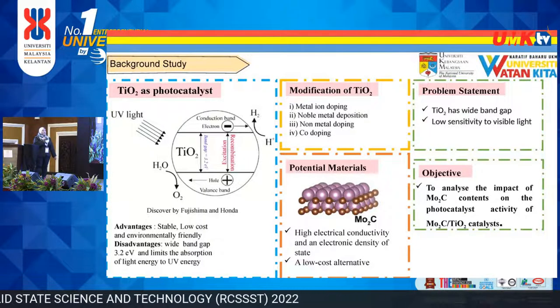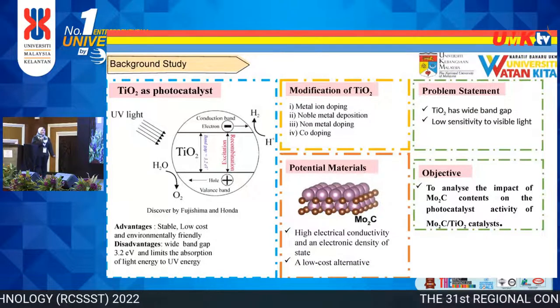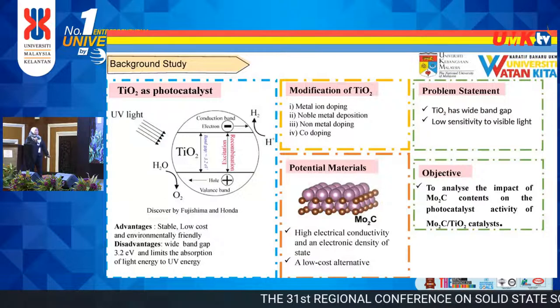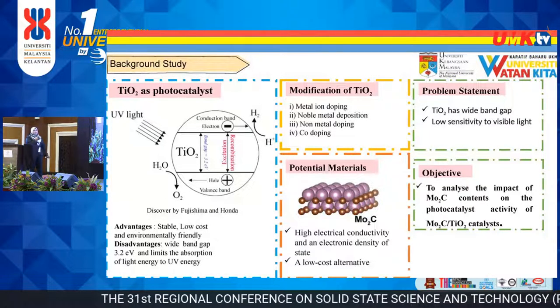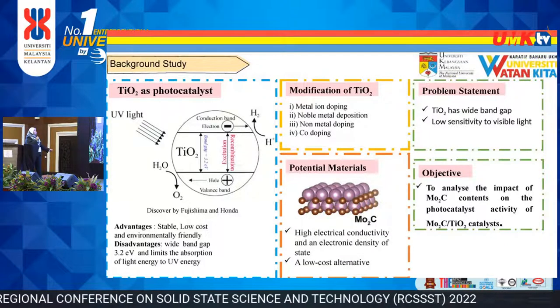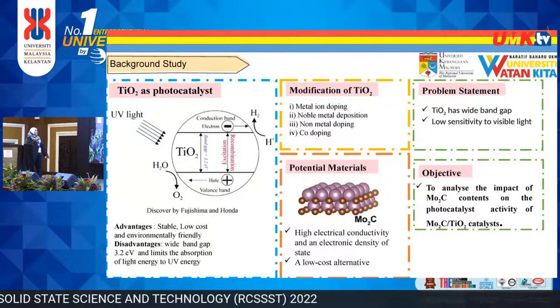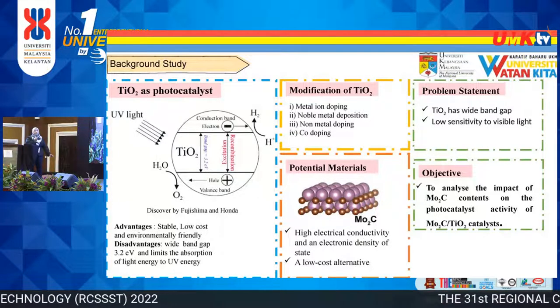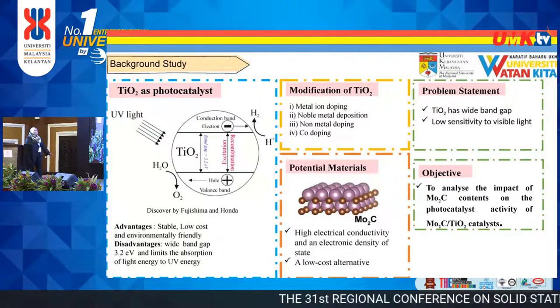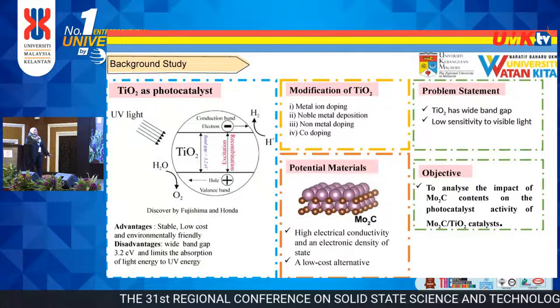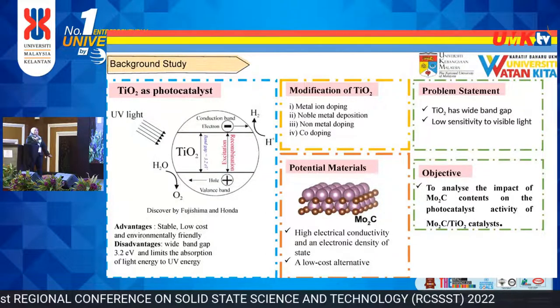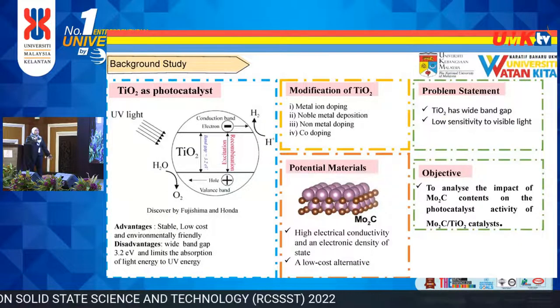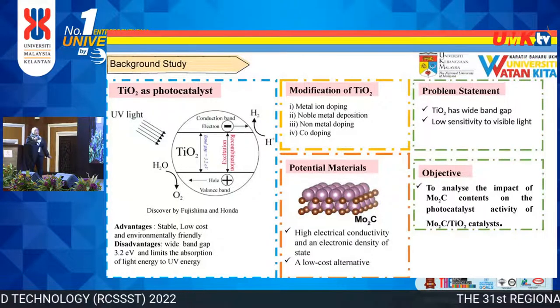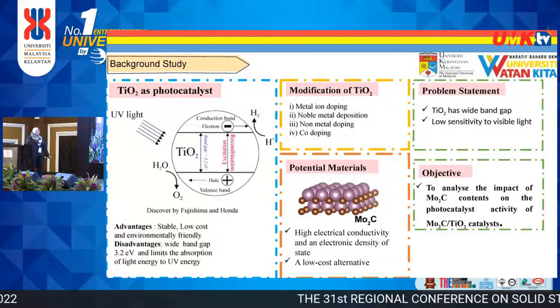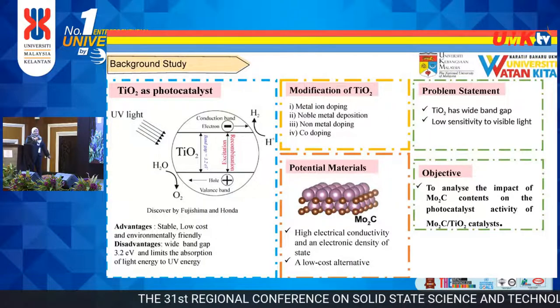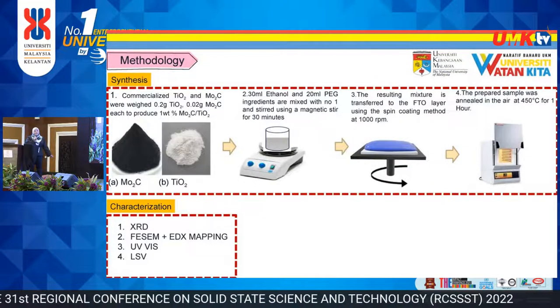The objective of this study is to analyze the impact of molybdenum carbide content on the photocatalytic activity of the molybdenum carbide with TiO2 catalyst. This is the method of synthesis: measuring the weight of commercialized TiO2 and molybdenum carbide to produce 1, 2, 3 and 4 weight percent of molybdenum carbide with TiO2, then mixing with ethanol and polyethylene glycol, and stirring using a magnetic stirrer for 30 minutes. The resulting mixture was transferred onto the FTO using the spin coating technique. Then the prepared sample was annealed in air at 450 degrees Celsius for 1 hour. The sample was then characterized using XRD, FESEM, EDX mapping, UV-Vis, and linear scan voltammetry.